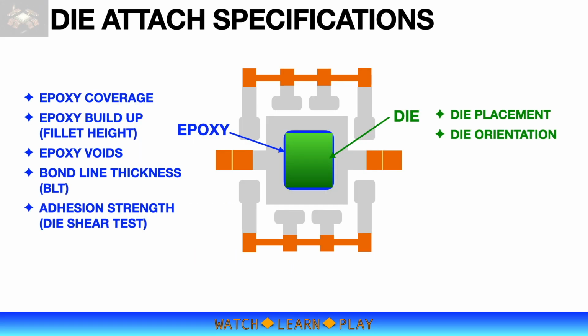The die attach process has certain specifications that are important and critical to device performance. Epoxy coverage is expected to be 100% under the die, and with visible epoxy fillet of at least 90% on each side of the die. If these requirements are not met, the device can be rejected due to quality concern.